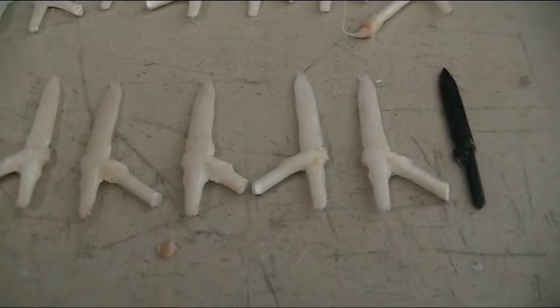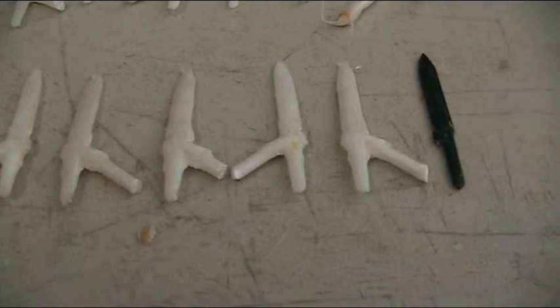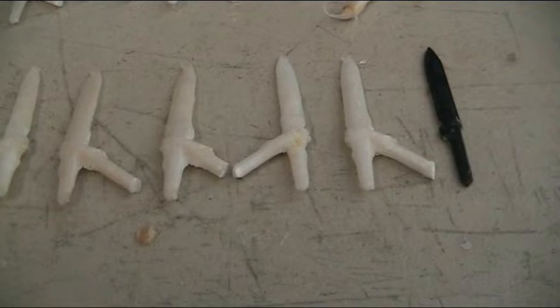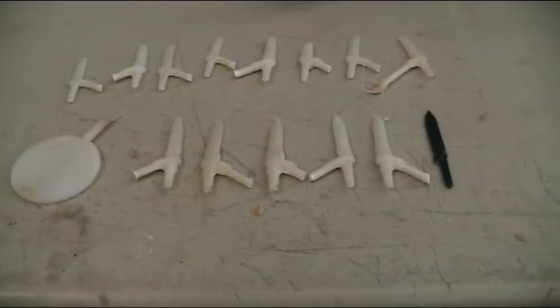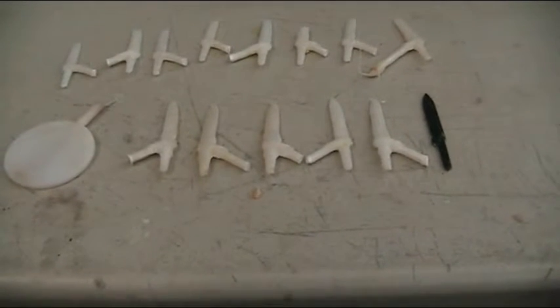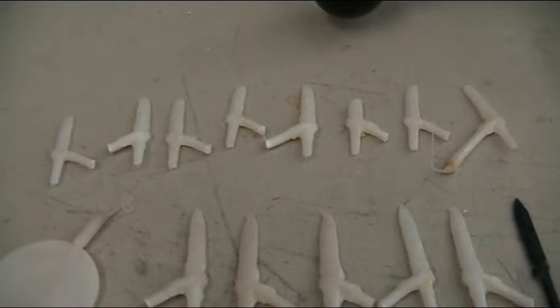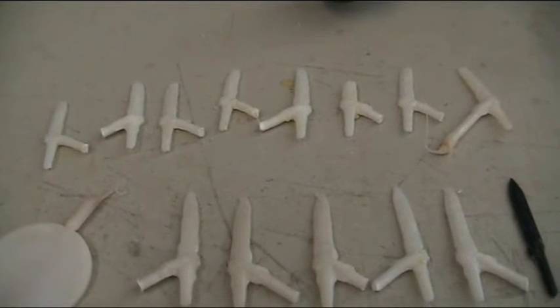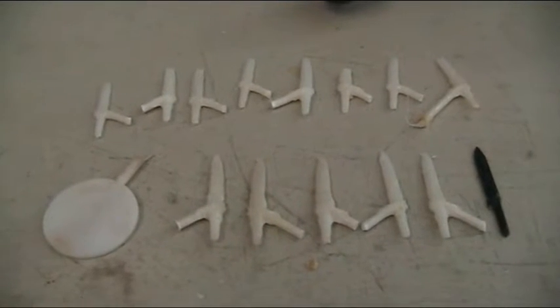But we've got problems that when the mold was pulled apart, it started to disintegrate. With every casting, it has taken a small chunk of the mold out and really deteriorated to the point where the part is unrecognizable and the form is just a strange blob. We've also had a problem that we couldn't get a full casting due to an airlock. There's all sorts of problems with the mold.